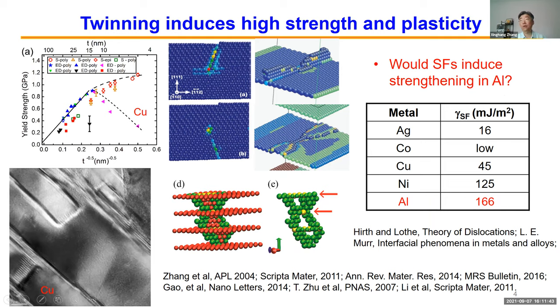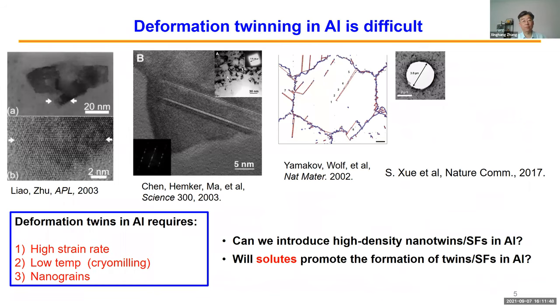And if we look at the answers to this question, it's been scattered in the literature in the past one or two decades, and you can introduce twins by deformation. So for example, by using cryomilling, which is ball milling at liquid nitrogen temperature, you can introduce deformation twins. Or if you perform nanoindentation, surrounding the nanoindent tips you can see some twin boundaries. This is just pure aluminum, which is quite remarkable.